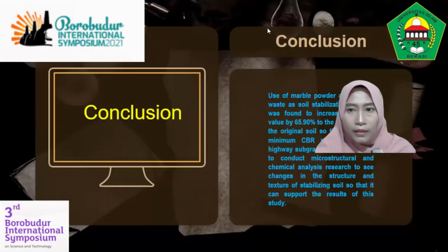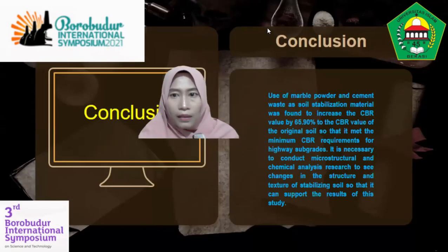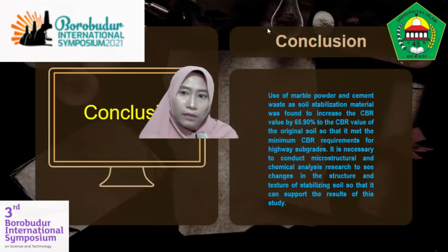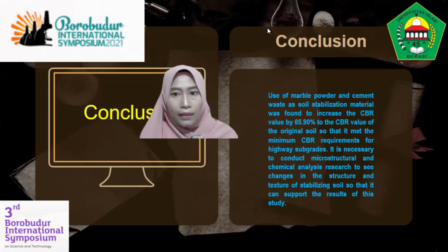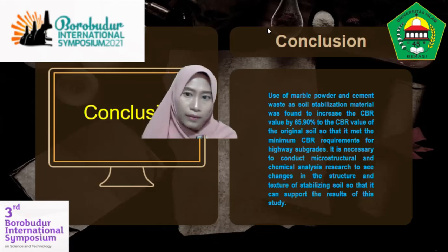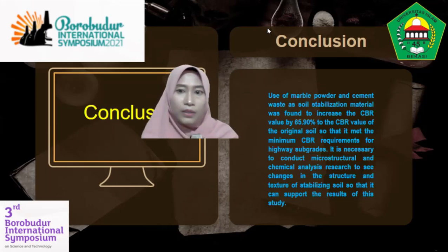The conclusion is the use of marble powder waste and cement as soil stabilization material was found to increase the CBR value by 65.90% to the CBR value of the original soil, so that it meets the minimum CBR requirement for highway subgrades. It is necessary to conduct microstructural and chemical analysis research to see changes in the structure and texture of stabilized soil so that it can support the results of this study.